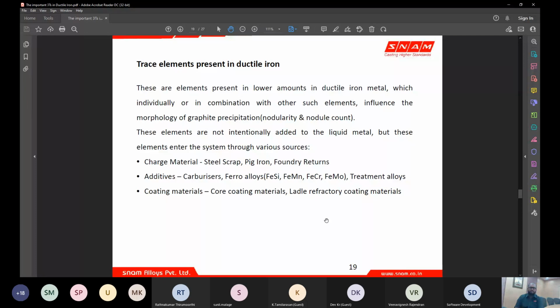Some elements cannot be measured using a spectrometer, or have less confidence or less accuracy in measurement using our conventional spectrometer available. So this is the reason why most of these elements go unnoticed, and their levels increase by themselves and have a direct impact. We only come to know about the impact of these elements after rejections come up. So what are the sources of these elements? They can come from the charge material, from our additives, or from the coating materials which we use in the process.